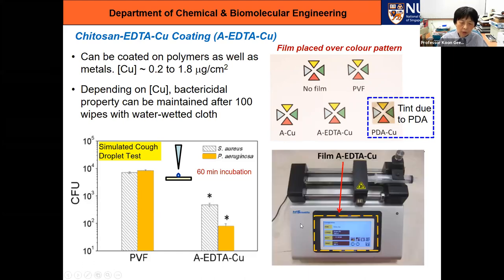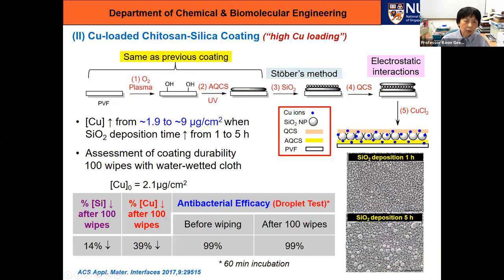And then we try it out. We put it over our syringe pump. We can see the readings pretty well, and the touch functionality was also preserved. But we want to try to do something with the high copper loading so they can last longer. So the first step is the same. We graft quaternized chitosan on PVF.